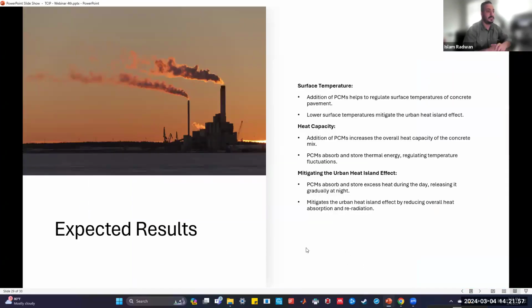Some of the expected results for the current research: of course, the surface temperature is going to be regulated due to the addition of the PCM, and also the heat capacity. As I mentioned, the heat capacity characteristic of the phase change material is really useful. So if we add it to the concrete mix, the concrete sample heat capacity is going to be increased too. And both of them are going to affect the mitigation of the urban heat island. As I mentioned, the PCM absorbs and stores excess heat during the day and releases it gradually at night.